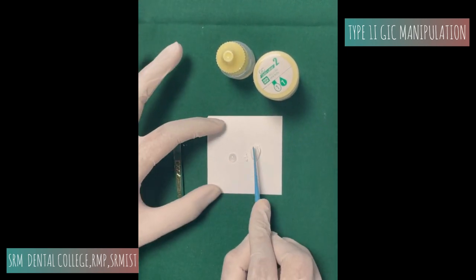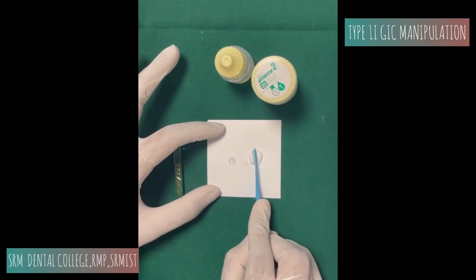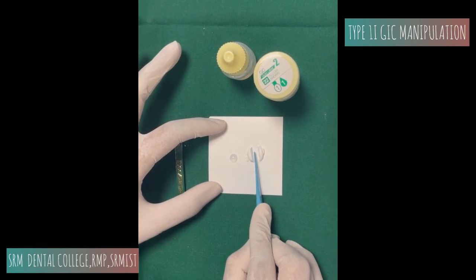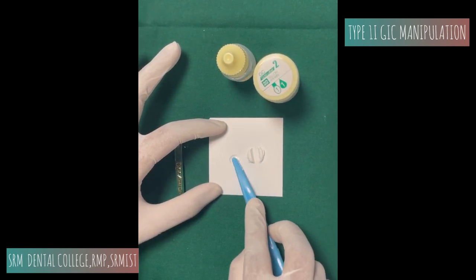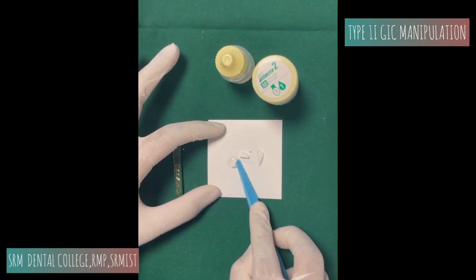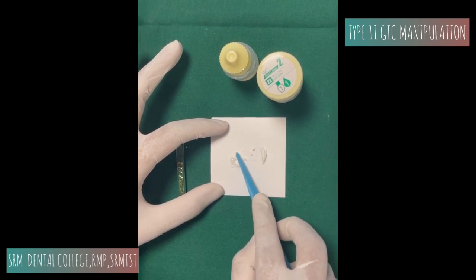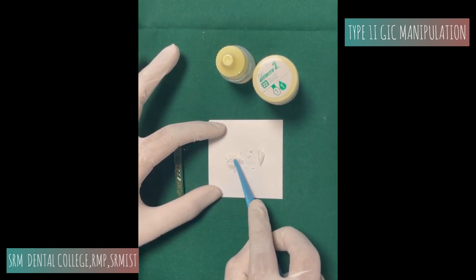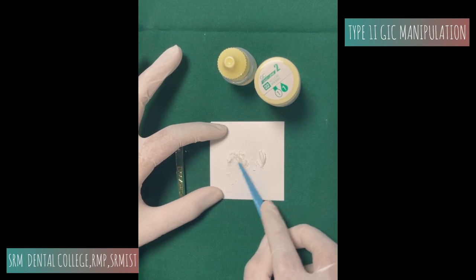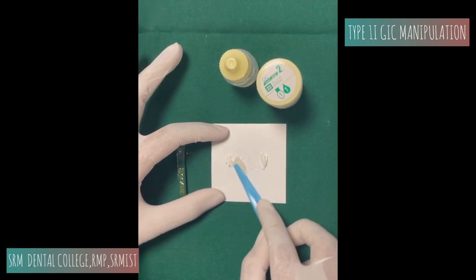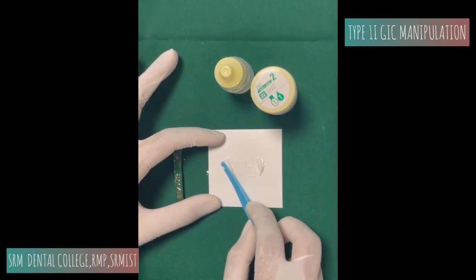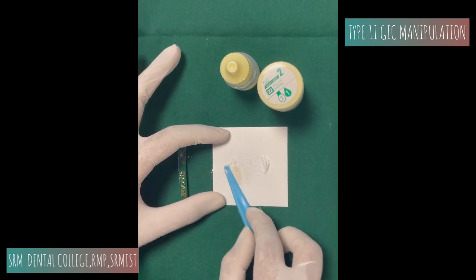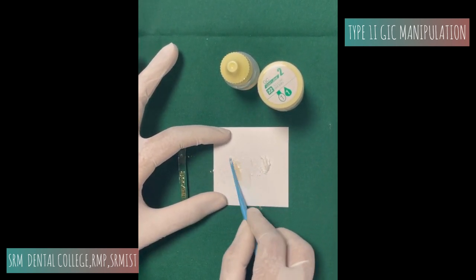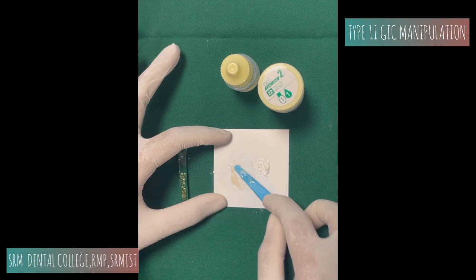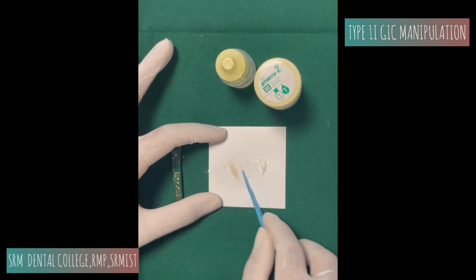Now divide the powder into 2 halves. Glass ionomer powder is never mixed in a round motion, it is mixed in a patting motion. So first half you take and you wet the particles. And now in a scooping or folding motion, you manipulate it for the first 5 seconds.